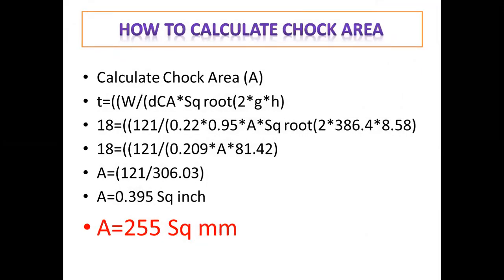So all these calculations are given. Choke area: T is equal to W upon D, C, A, square root. W is the weight, D is the density of molten metal, then 0.22. C is the choke area. A is the CA, square root of 2GH. H is the effective pouring head. G is the gravity acceleration, from the height we are doing the pouring. Considering the cope box height, this velocity is taken into consideration. The answer will first be 0.395 square inches. If you convert into square millimeters, that will be 255.